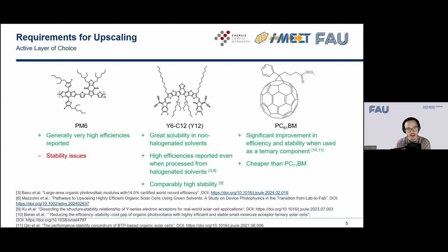And to add up in efficiency and stability, we added a slight amount of PC60BM into the active layer because it helps with charge dissociation. And since it's a great radical scavenger, it also helps with stability in ternary systems. And it's cheaper than PC71BM, where we didn't find any big differences in efficiency.